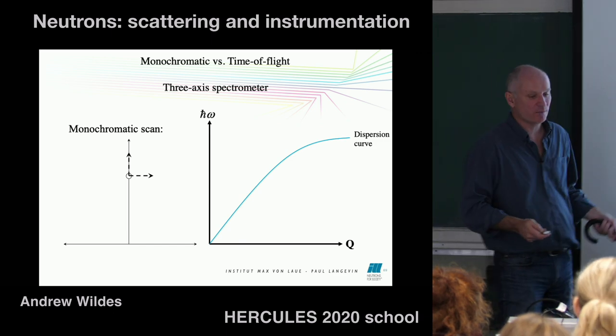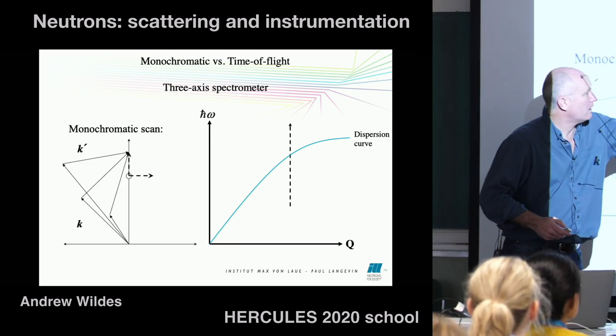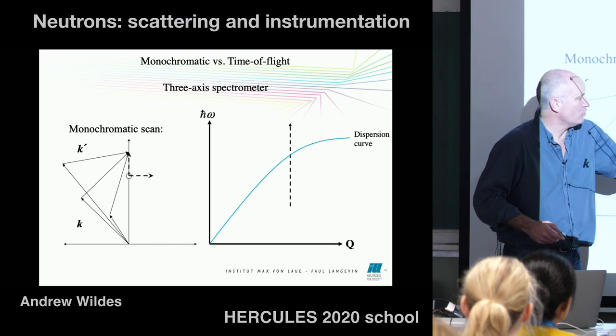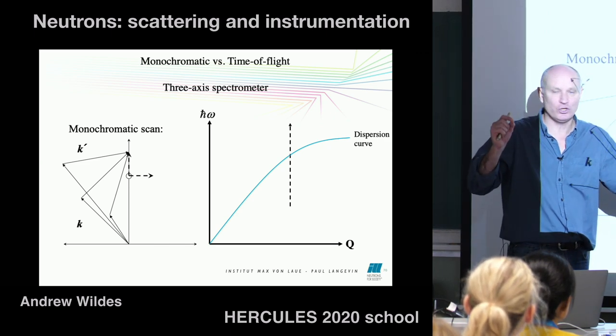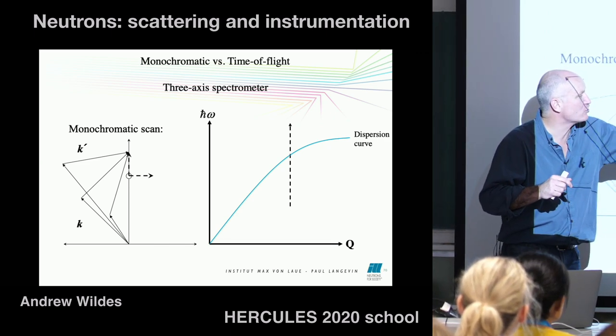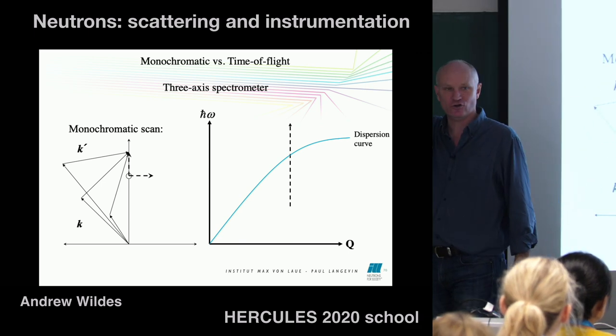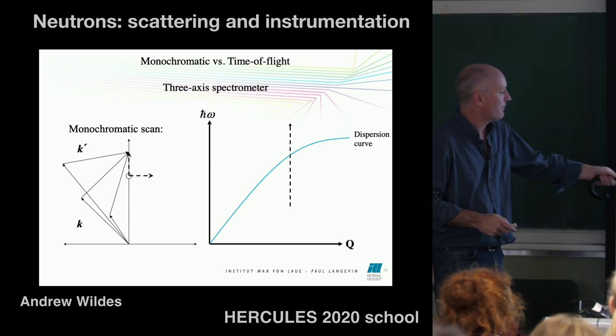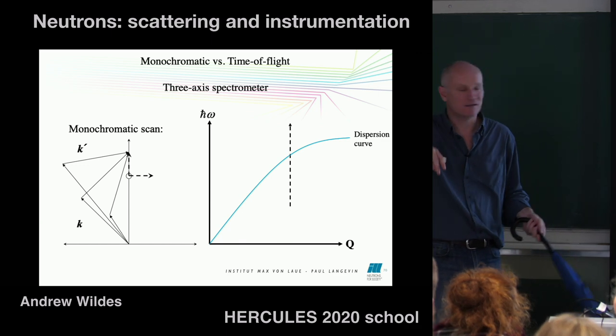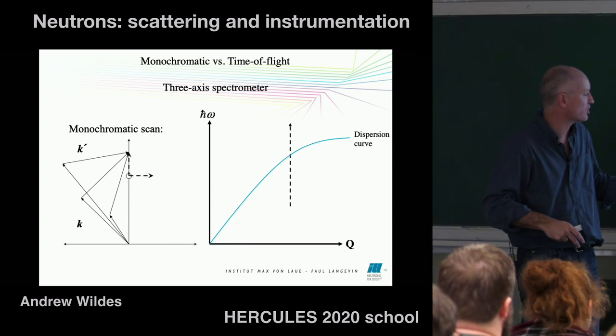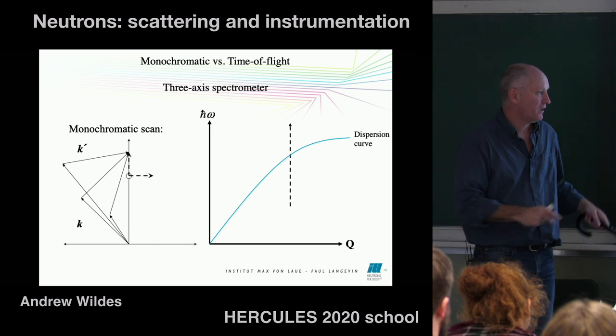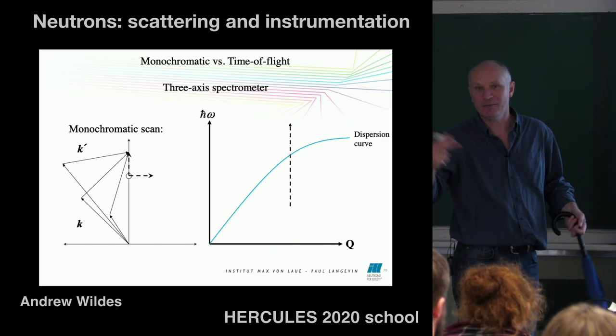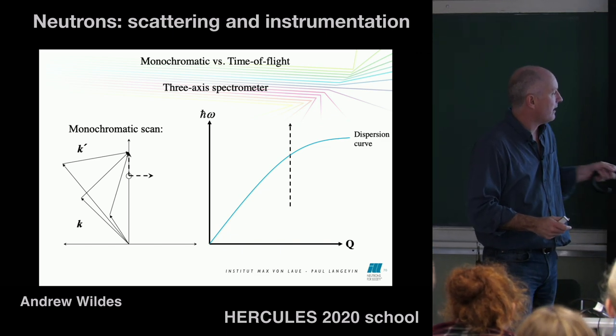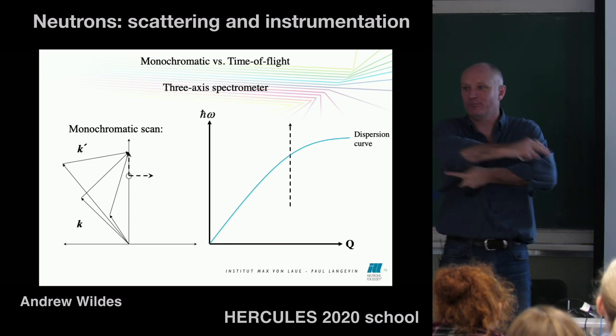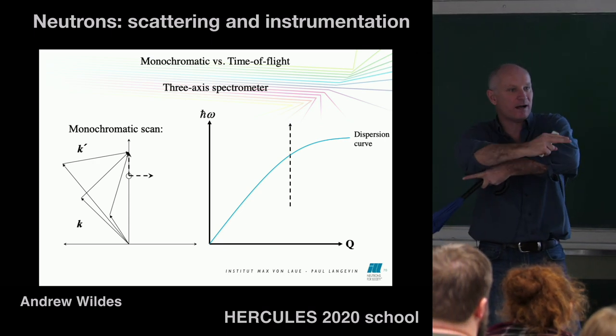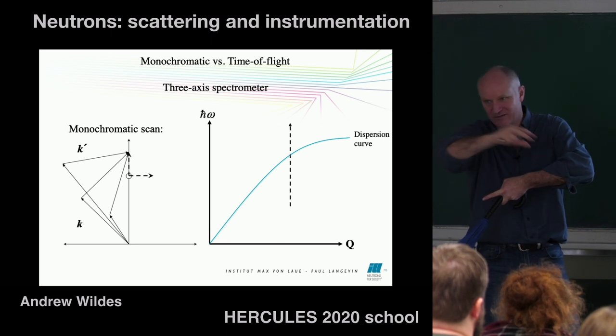If you wanted to do a measurement, for example, along this direction, you would change the energy for a fixed Q, and you would go point by point, and you should get a nice peak where the neutrons are interacting with the phonons. But that means you've got to do a rather complicated series of motions on your instrument. You need to change the angle of the crystal, you need to change the angle of the monochromator, and possibly the analyzer, and you also need to change the angle between the incident and the final beams, effectively moving your detector around the sample.